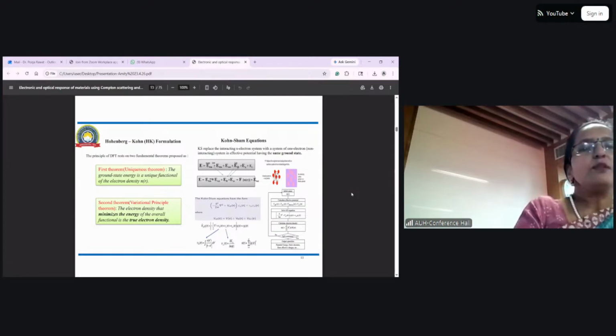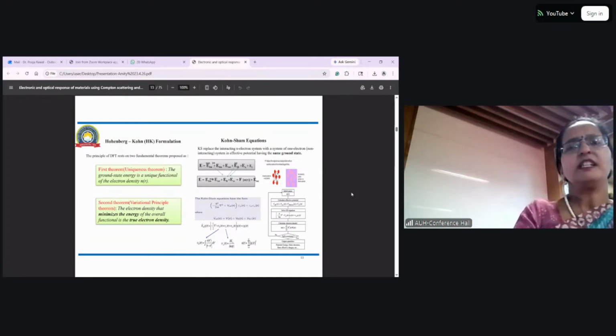So what we do in density functional theory is start with an initial guess of the density of the system. Then we calculate the different parameters and check for self-consistency. If the result is the same as what we proposed, then we go further. We calculate the energy there and try to obtain the minimum energy. If the result is not the same, we again start with an initial guess of the electron density.